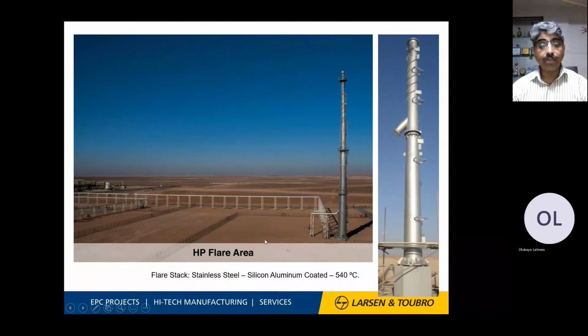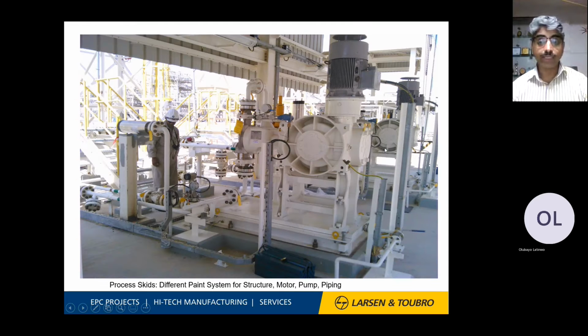This is all high pressure flare area. These are all the lines and this is all the piping which we see. So this is always at high temperature, 540 degrees centigrade. The paint is silicone aluminum. This is for the stainless steel stack because the chimney is always operated at high temperature. So structures are always withstanding high temperature. Carbon steel can withstand up to 450 or 425 degrees centigrade temperature. So normally these structures are of stainless steel.